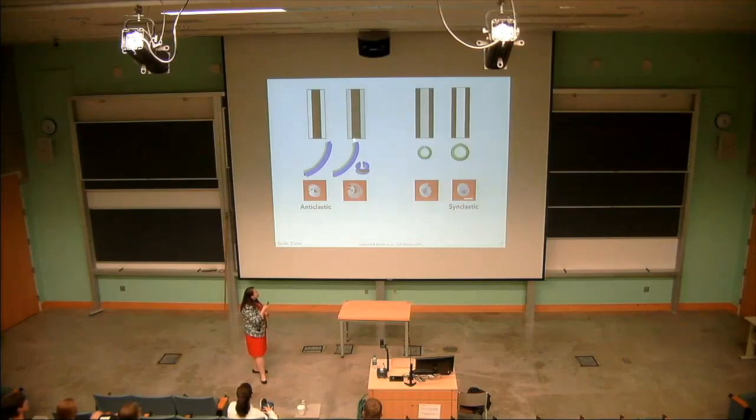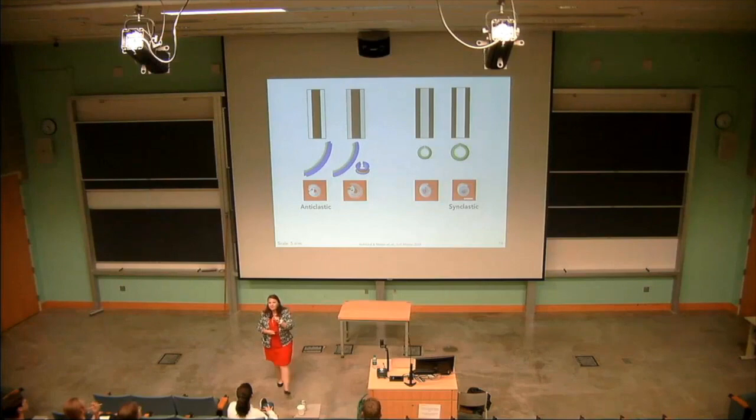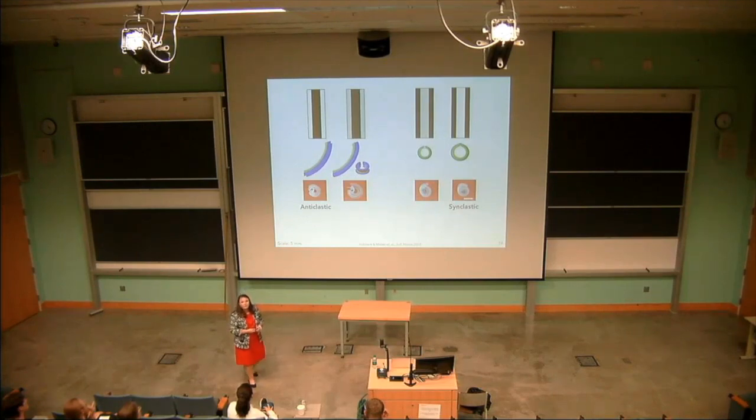In this case, if you place a dark gray ink, so 80% ink density in one region, and then 20% ink density in another region, the image is just slightly muted here. But in this case, what we're doing is we're darkening the portions that are going to be activated, and then all of the other regions that had no ink now have just a small amount of ink, 20% ink density. And the reason for this is to soften those regions ever so slightly. So now they're open to more movement. You can see how the images actually changed, not very much experimentally, but we do actually see a smaller radius of curvature for our structures that are allowed to fully soften.